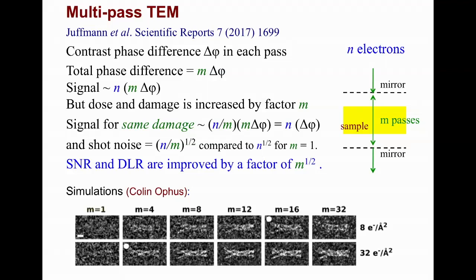This increases the phase signal by a factor of m, but also increases specimen damage by the same factor. However, we can avoid this extra damage by using m times fewer electrons, resulting in a multipass phase signal that is the same as for N electrons passing through once. And since we used m times fewer electrons, the statistical uncertainty in the signal is reduced. Consequently, the shot noise, the signal-to-noise ratio, and the dose-limited resolution should all be improved by a factor of √m.